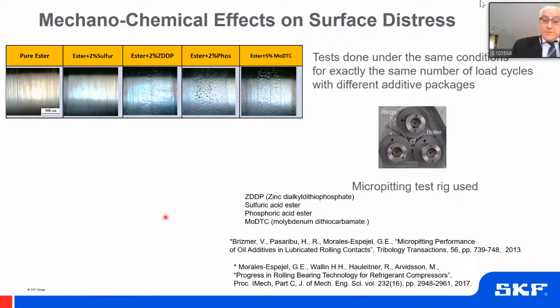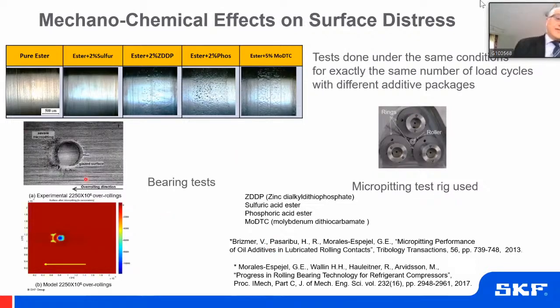So another way to study micropitting experimentally is actually by introducing indentations on the raceways, because immediately you will generate micropitting around this raised material, and especially in this area, which is normally the exit of the overrolling. So if you have a ball that is overrolling in this direction, this will be the exit point, and we call it the trailing edge of the dent. And normally here you generate more surface stress, as can be modeled as well. The model will also give you more surface stress here. And this is due to the fact that here we have slightly higher hydrodynamic pressures.